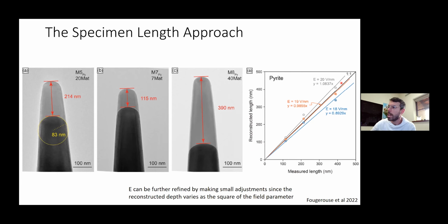And after we have made these iterative values, we can further refine them by making small adjustments so that we have a perfect one-to-one average line between the reconstructed and the measured length.